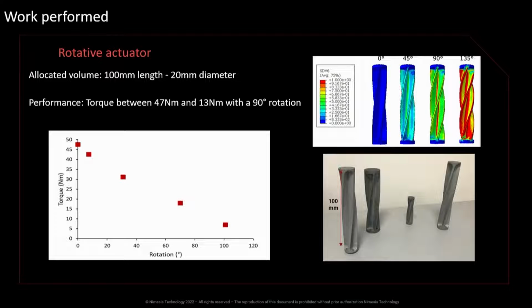And finally, we manufactured some first prototypes of actuators. So we selected a rotative actuator. Here the idea is that this actuator shall give a rotation up to 90 degrees. And so we measure the stress during the transformation inside the prototype. And we also measure the torque given by the actuator during the rotation. So we can see that the torque at the beginning is almost 50 Newton meters, and then will decrease quite significantly during the rotation, up to 13 Newton meters.